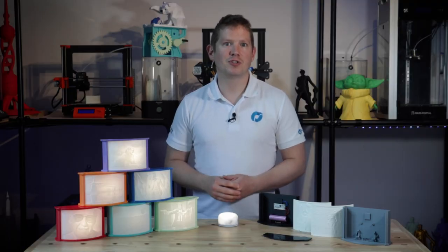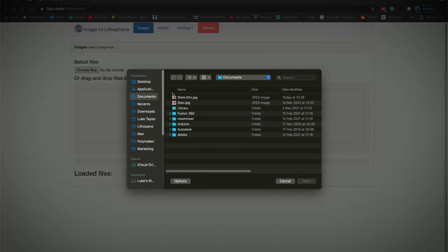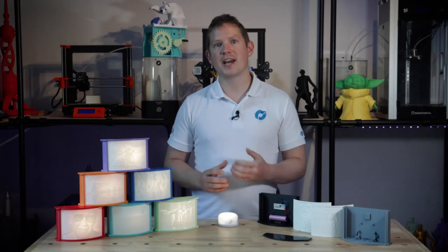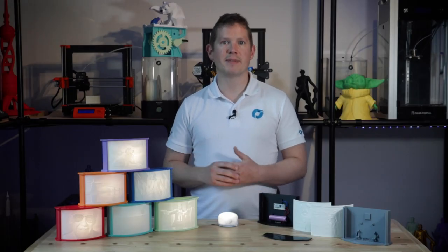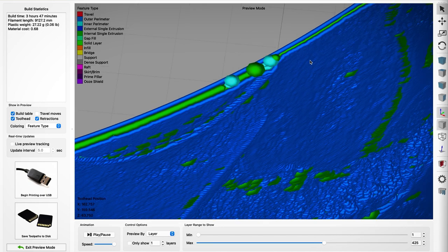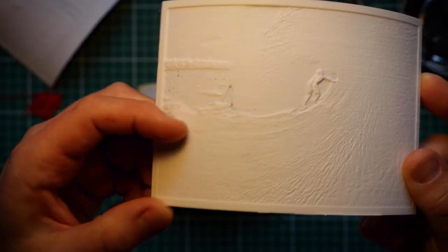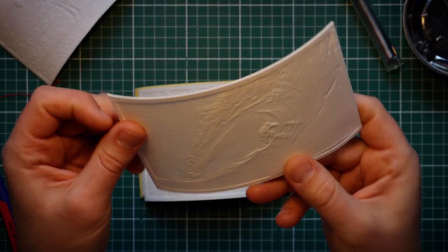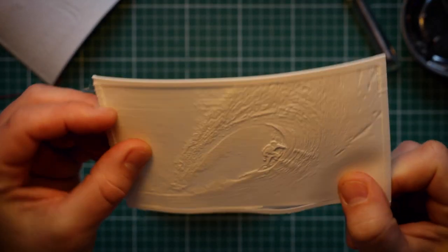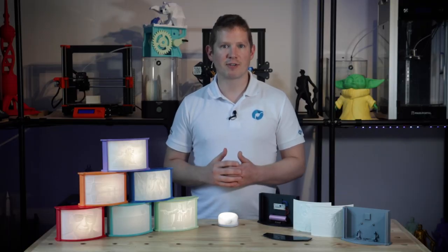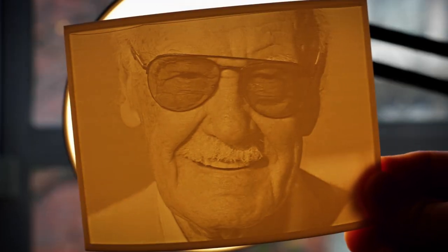This website allows you to choose the minimum and maximum thicknesses, and all values in between will serve as the grayscale. As I'll be printing with a 0.4mm nozzle, I have set the minimum thickness to 0.8mm so that two perimeters make up the lightest, thinnest parts. I've played around with having a single shell extrusion and also thicker maximums, but finally I think that with the lights I have, a maximum of 2mm works best, and a minimum of 0.8mm provides enough range in the grayscale to provide a clean, even image.